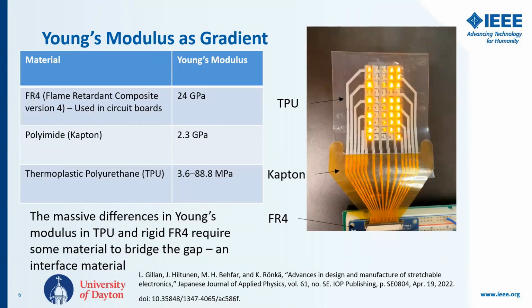In order to alleviate that, we can take another material that has a Young's modulus in between our soft and our hard materials and place it in between. We've been using Kapton, or polyimide film, in our lab. And this provides some way to bridge the gap between hard and soft materials.